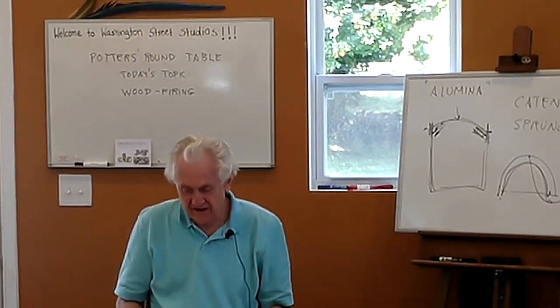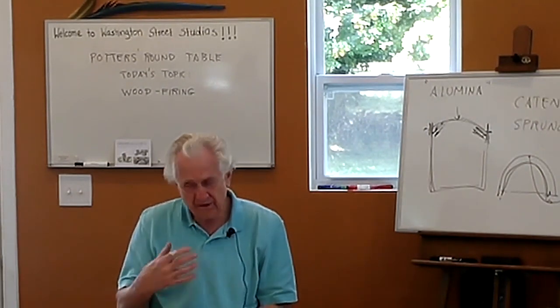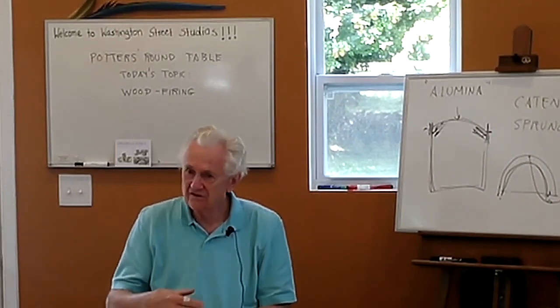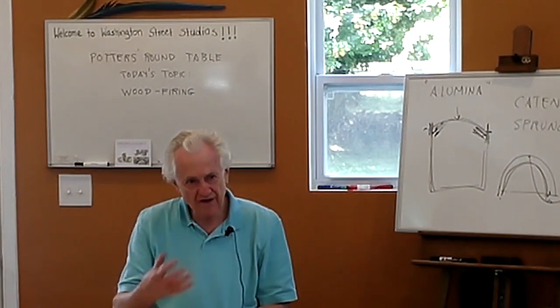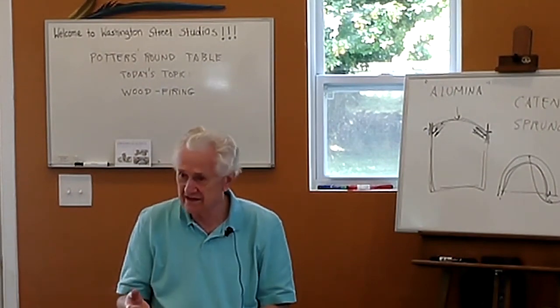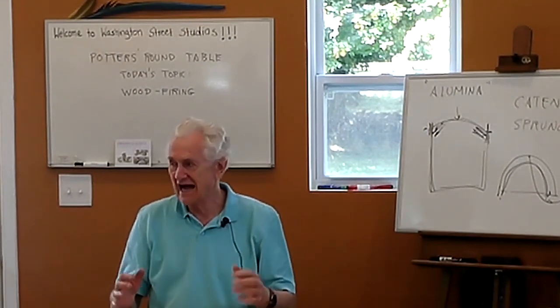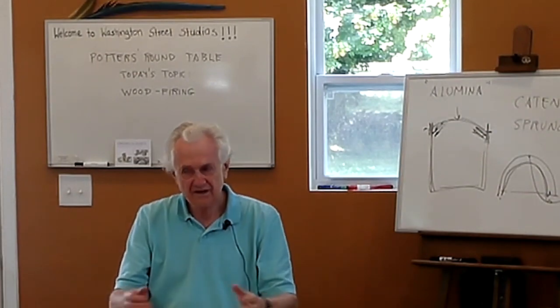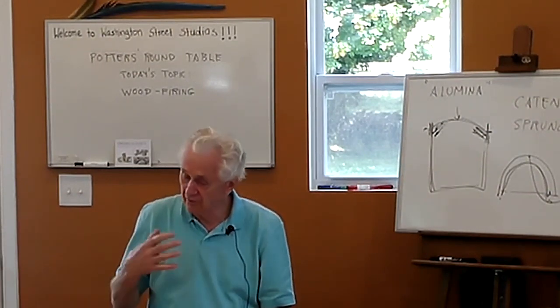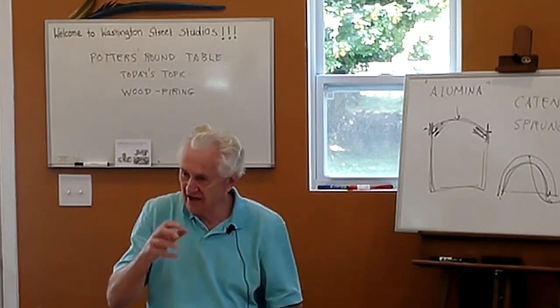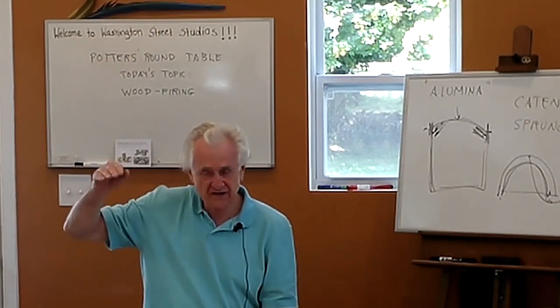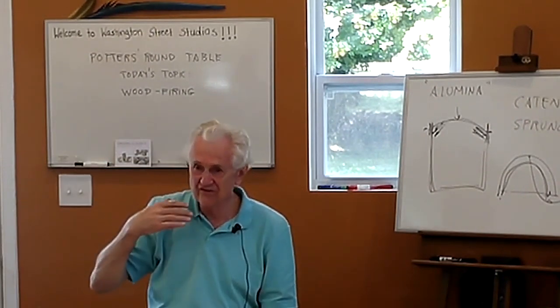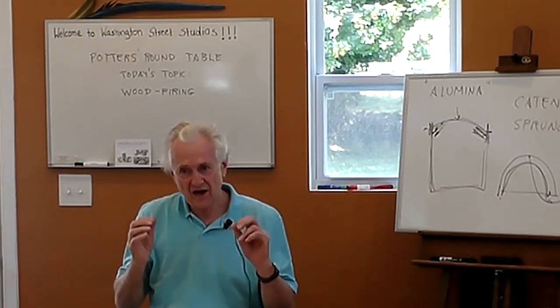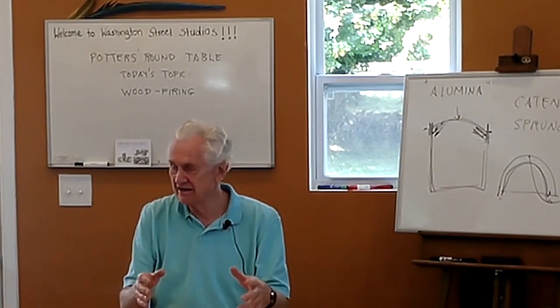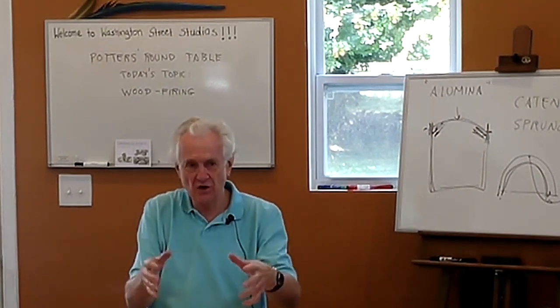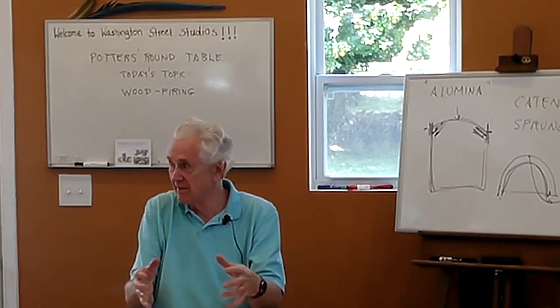And what this leads to at some point is you establish what you call a stoking cycle. For every kiln, you go into some kind of rhythm that's best for that kiln, as to how much fuel I load and how often I put it in. Because what you're trying to do is get the best amount of heat out of it, and keep the temperature continuing to rise. And this is part of the art, knowing how much fuel to put in and when to put it in. If I put in too much fuel, it chokes the fire, and it might almost go out.